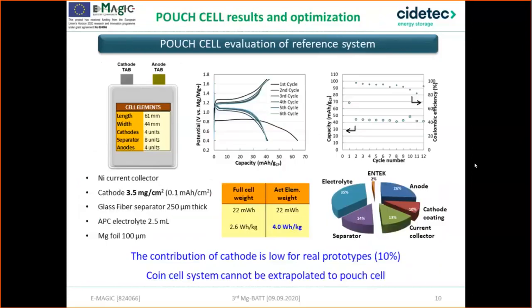The first approach to pouch cell was transferring the conditions of coin cell level to pouch cell level. That is to say, keeping the cathode loading usually used at coin cell level, 3.5 milligrams per square centimeter, a fixed separator based on glass fiber, high volume of electrolyte, and relatively thick anode foil, up to 100 micrometers.